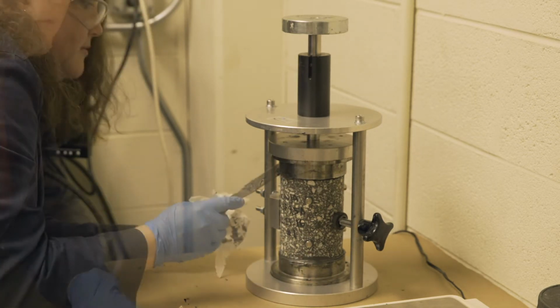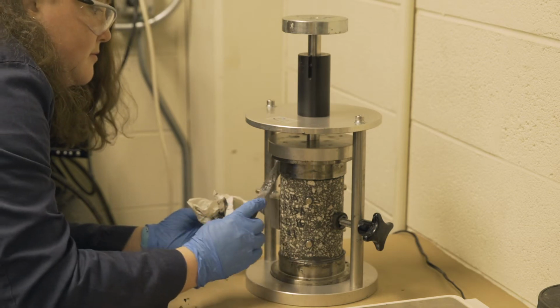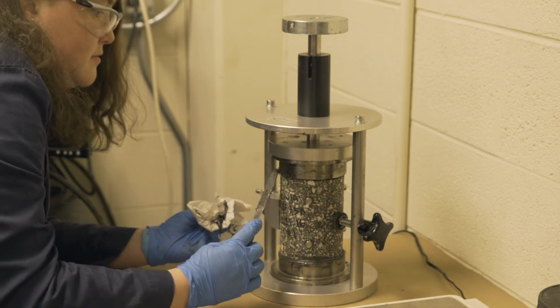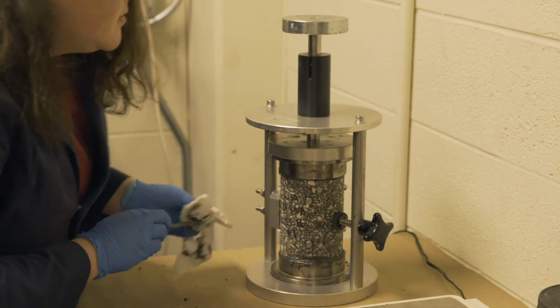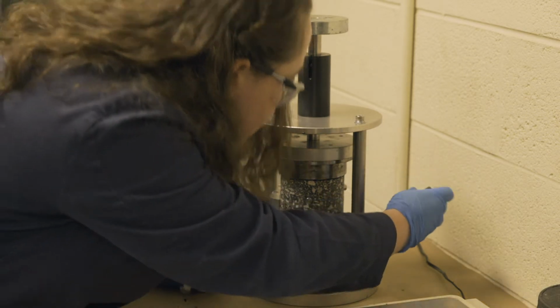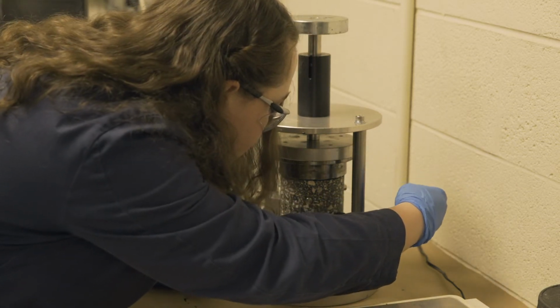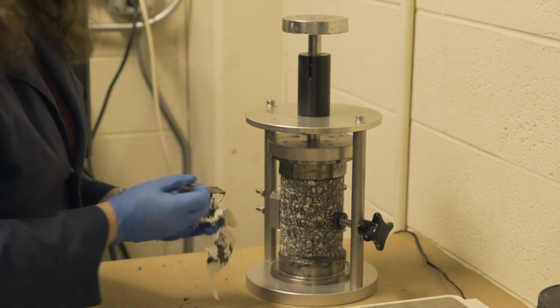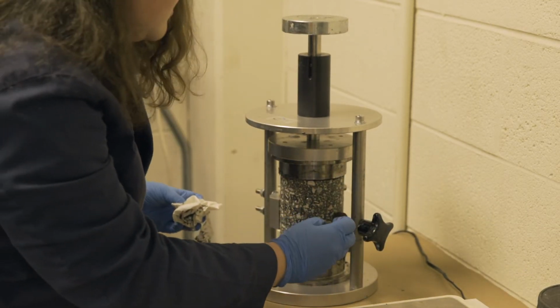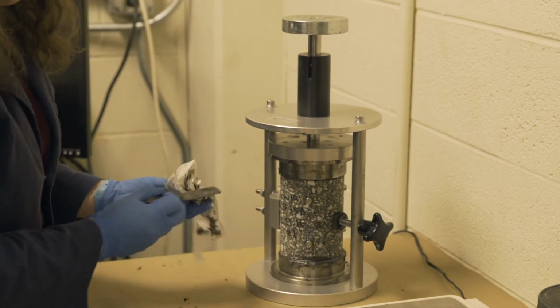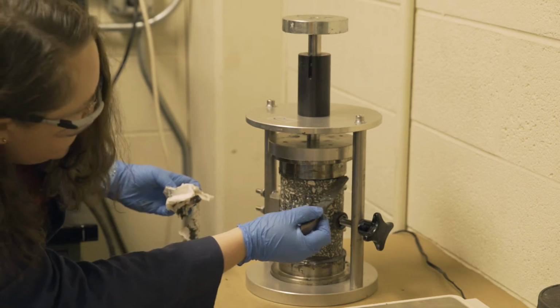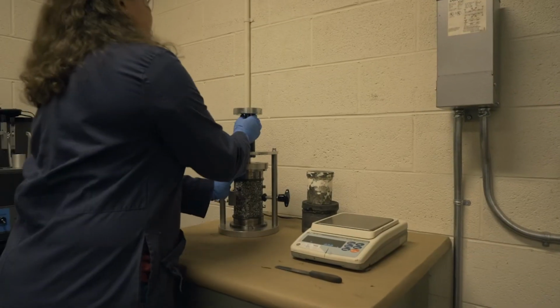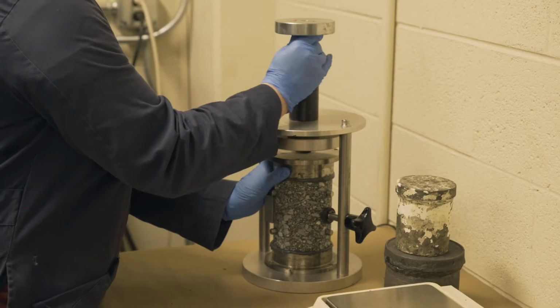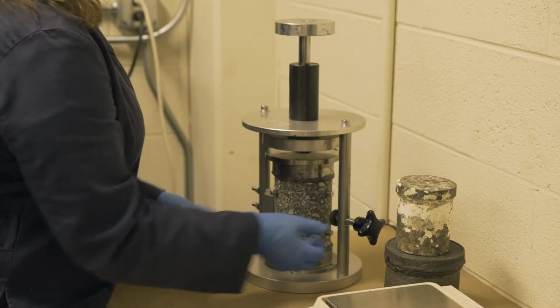If glue is not squeezing out in a certain area, a void may exist in the glue and cause failure in the fatigue testing. Allow the epoxy to reach the initial set before removing the specimen from the gluing jig. For this epoxy, the initial set will take approximately 4 hours. This epoxy will be completely set within 24 hours. After the epoxy has set, remove the specimen from the jig, taking care to lift by the bottom platen.